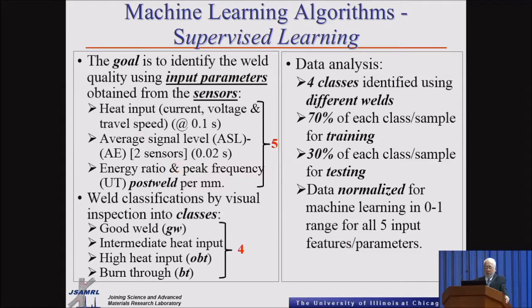Again, the goal was to identify the input parameters from the sensors, which in this case are the heat input, the average signal with the two sensors, and the energy ratio and peak frequency, which also has two channels. That data was collected at about a tenth of a second. The average signal level was collected at 50ths of a second, and the energy ratio and peak frequency was collected per length, per millimeter.